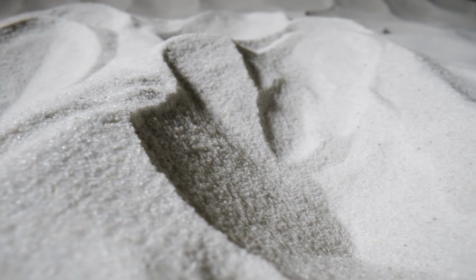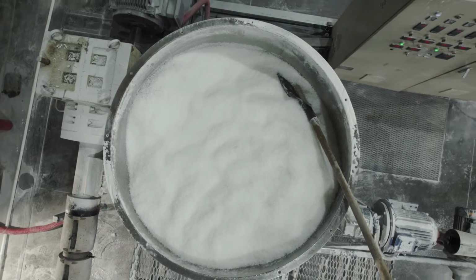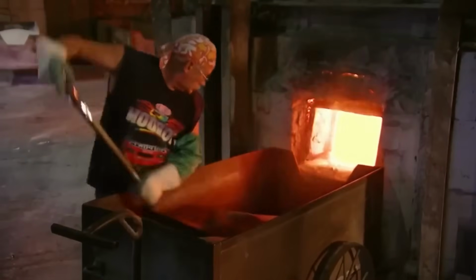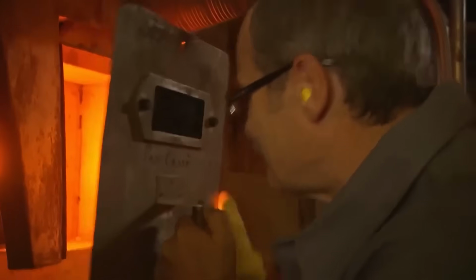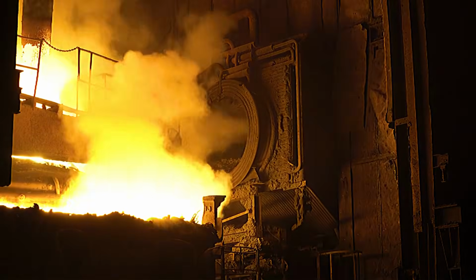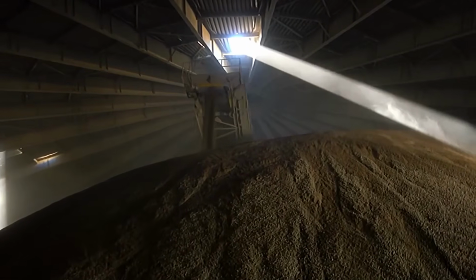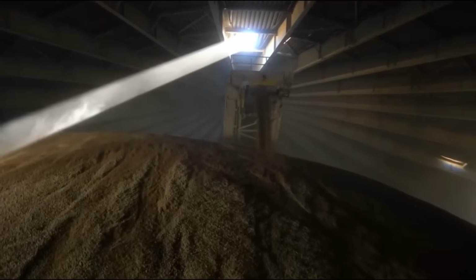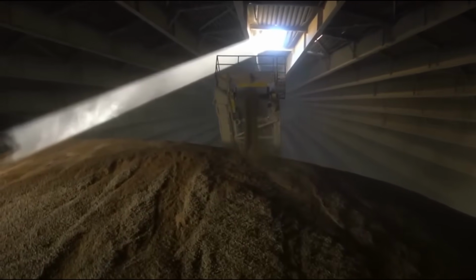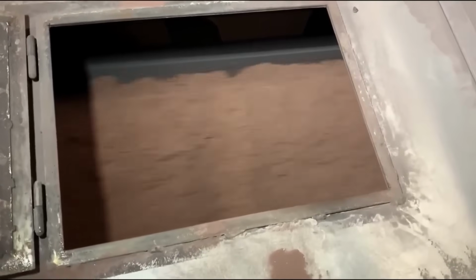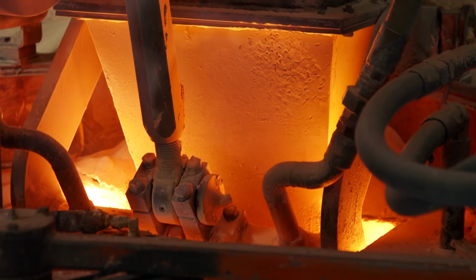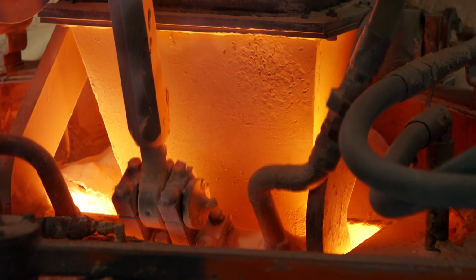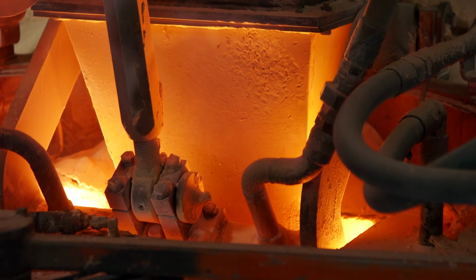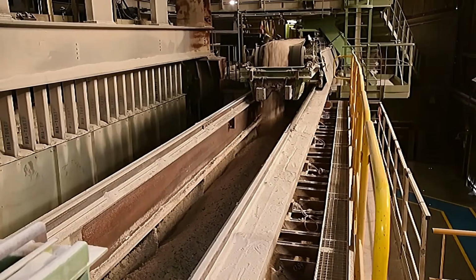Inside the factory, the silica does not go directly into a furnace. It is first combined with 2 additional compounds that change its behavior entirely. Sodium carbonate, soda ash, lowers the melting point of pure silica from approximately 1,710 degrees down to around 1,000 degrees, reducing the energy required to achieve a workable melt. Calcium carbonate is added to improve chemical durability.